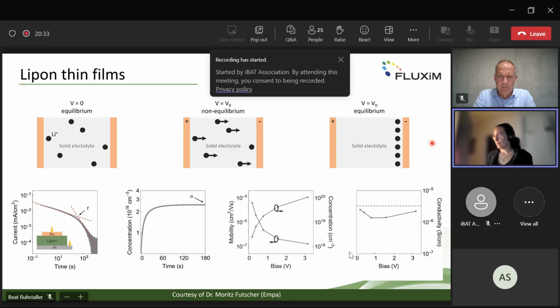So this is rather simple and has been done for multiple variations. Moritz did some thickness variation, and here it's shown that he also varied the bias, because the idea is that if you go to a higher bias voltage, you accumulate more charges, and so there is a limit at high bias, and then you would get the real ionic conductivity density.